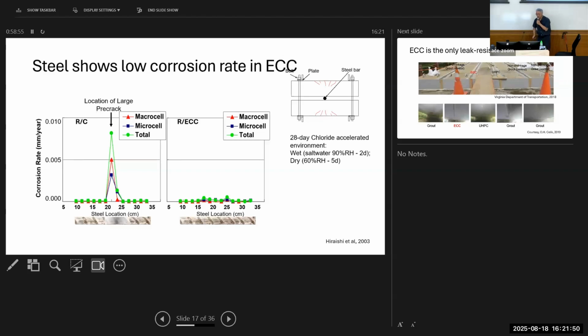Okay, so if you don't believe what I just showed you from our laboratory, this is another experiment carried out by a group in Japan, actually quite some time ago. And they did a very interesting experiment. They put two beams with a steel bar below them, with nuts there, with the steel in between those two beams, causing tension here and tension there, and keeping the cracks open there, and then exposed the whole specimen assembly to an accelerated chloride environment.